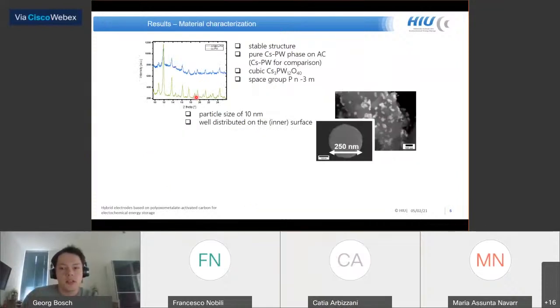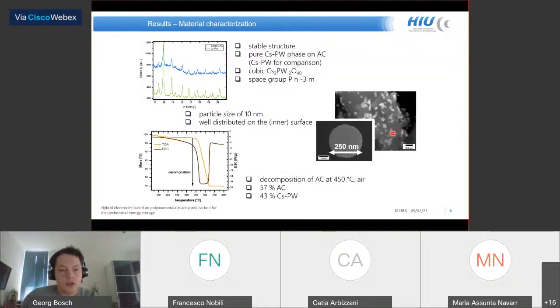The green XRD pattern shows the reflexes of the pure polyoxometalate material, which can also be found in the blue pattern of the hybrid material and confirms the stable structure. Compared to the SEM picture of the pure polyoxometalate particle in the front with a diameter of around 250 nanometers, the hybrid materials show well dispersed polyoxometalate particles on the activated carbon with a particle size of around 10 nanometers, and thermogravimetric analysis shows a composition of 57% of activated carbon and 43% of polyoxometalate particles.